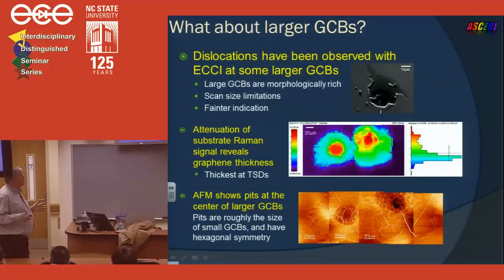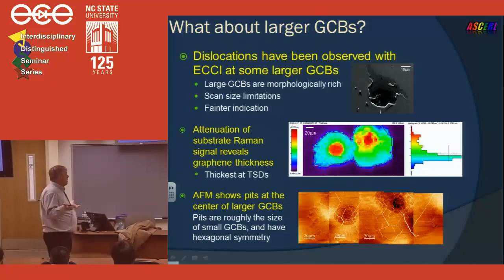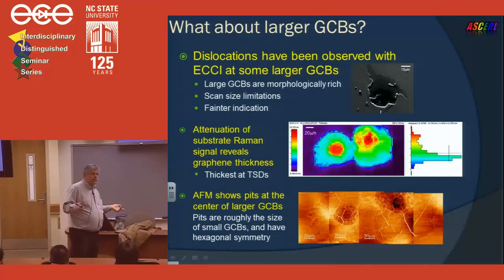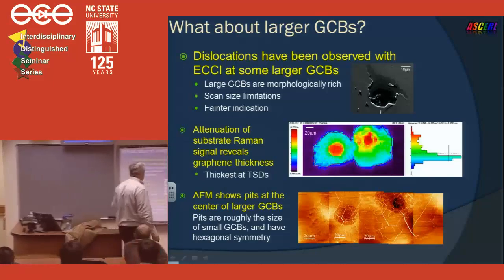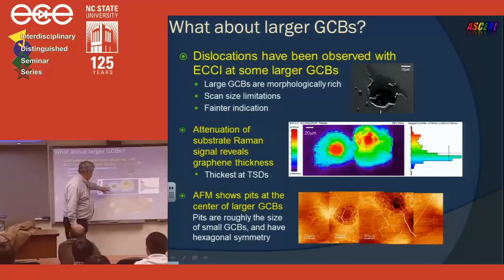Now, let's look at some of these graphene-covered basins, but now we're going to use Raman. And we can use Raman in another way. We can use the attenuation of the Raman beam to measure the thickness. And so that's a very convenient process. And so here's two graphene-covered basins, and this is the Raman, and this is the AFM. And they are approximately the same size, so you can overlay them in your mind's eye. The thickness, the red areas, is the thicker areas, and the edge, which is blue and green, is the thinner areas. And it's sort of hard to read here, but basically it goes from about 1 nanometer to about 14 nanometers. So it's pretty thick in the center.